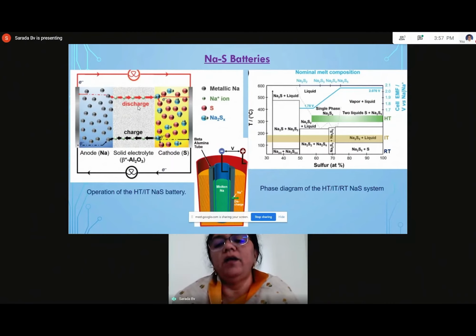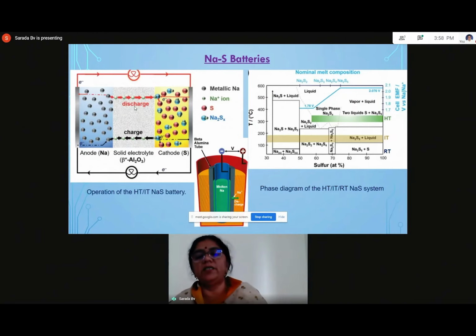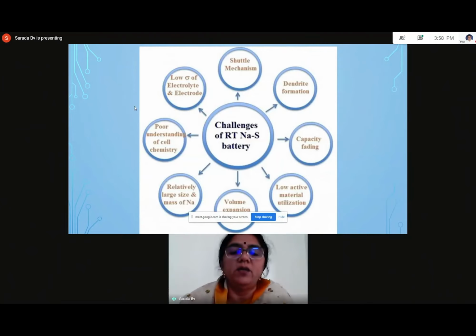And these high order sodium polysulfides, which are formed during the discharge process, deteriorate the performance of sodium by forming dendritic structures, and this has to be controlled by using proper anode and also cathode sulfur. So as mentioned in the case of lithium sulfur batteries, here also you have to take proper care of sulfur as cathode, and in addition we also need to find more types of anodes for the sodium sulfur batteries. So these are all the challenges for room temperature sodium sulfur batteries: the low conductivity of electrolyte and electrode, and the shuttle mechanism, as I mentioned, formation of polysulfides and their dissolution into the electrolytes, which causes most of the problems, and dendrite formation at the anode.